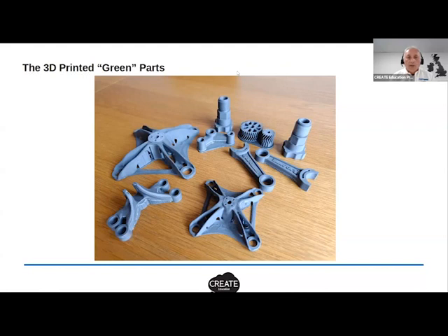So the polymer content allows the material to print like a polymer, even though it's got a very, very high metal content. This is how they look when they come off the printer. They've got this very dull grey finish. It's not easy perhaps to see, but on a couple of models you might see a very thin layer of white visible in certain areas, and that is the ceramic support layer. What that's doing is creating a barrier between the support materials for these parts and the part itself.